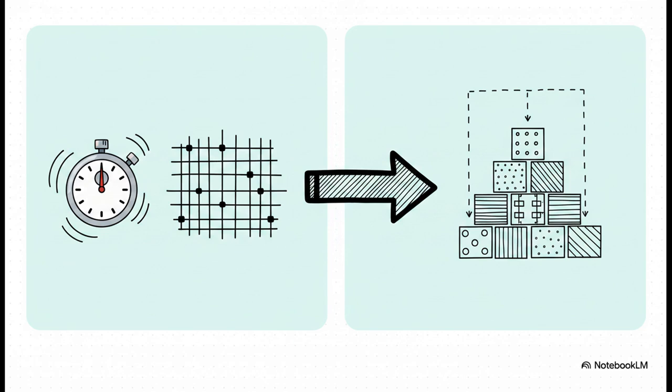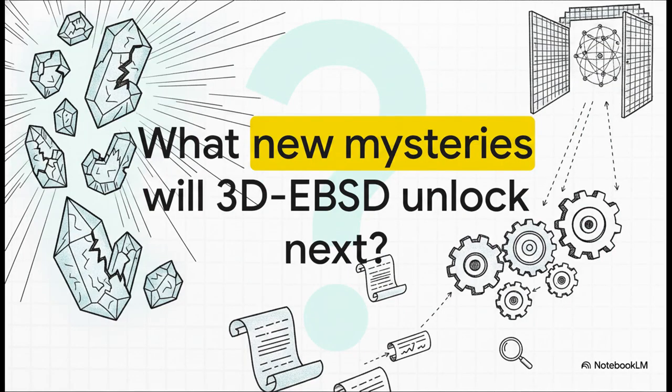But the future? We are moving straight toward dictionary indexing. Instead of relying on the Hough Transform to mathematically find those lines, AI will soon just compare raw, real-world patterns directly against libraries containing millions of simulated ones. This massive shift means we're soon going to be able to read heavily deformed, super complex samples that were previously considered completely impossible to index. It really leaves us wondering what previously invisible materials we'll be able to decode next.